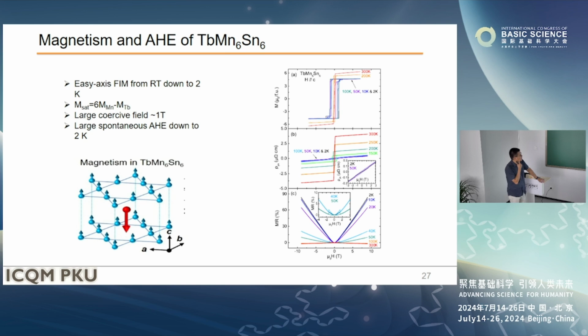Okay, what is our observation? So we find an easy-axis ferrimagnetic state from room temperature down to 2 Kelvin, and all the manganese moments are pointing up and the terbium is pointing down. The saturated magnetization equals 6 manganese minus 1 terbium, and a large coercive field around 1 Tesla, so it's a hard magnet. And this magnetization you can see very clearly, right? And also, more important, we measured the anomalous Hall effect. You see the Hall signal just follows the shape of the magnetization, meaning it's a very clear anomalous Hall effect, even down to 2 Kelvin.